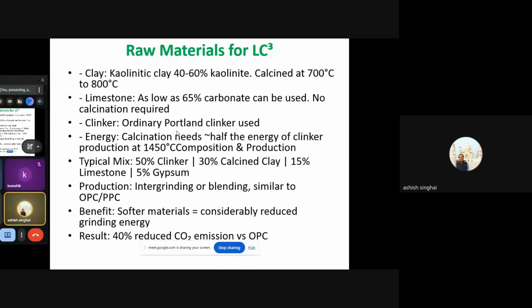Now, what are the basic raw materials? Just to understand the basic composition. It consists of kaolinite, which is basically what we call calcined clay. It is about 40 to 60%. Ideally, it is about 50%. It is calcined at about 700 to 800 degrees Celsius. The second element is limestone. As low as 65% carbonate can be used.